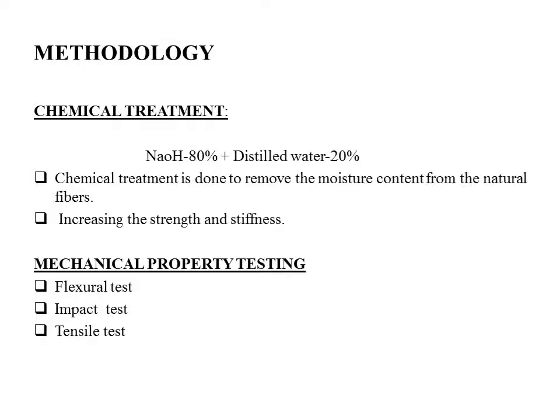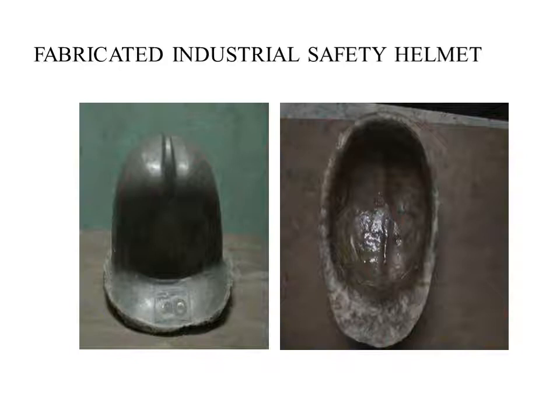Methodology: chemical treatment. 80% of sodium hydroxide mixed with distilled water at 20%. The chemical treatment is done to remove the moisture content from the natural fiber, increasing the strength and stiffness. Mechanical property testings: flexural test, impact test, tensile test. Fabricated industrial safety helmet. This is our fabricated helmet.